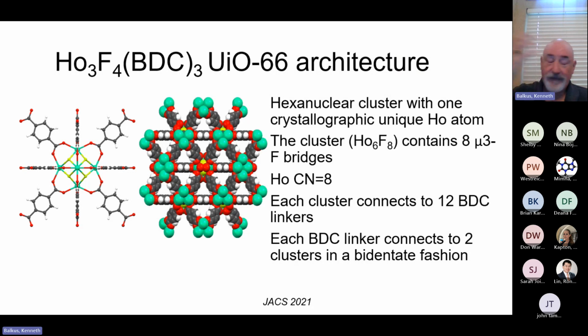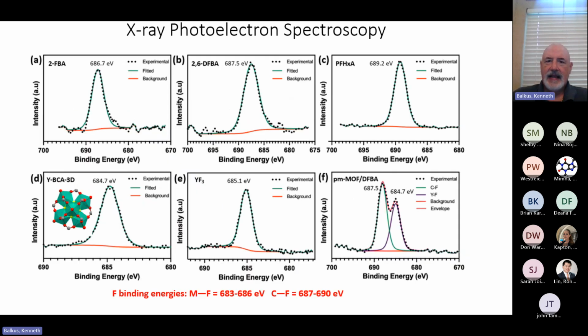And then the first question you ask is, is it really fluorine? Because if you think about where oxygen and fluorine are in the periodic table, in crystallography it's very difficult to prove that it's oxygen or fluorine. Fluorine fits better in terms of refining the structure, but it's not really proof. So we needed some other evidence that we were making fluoro bridge clusters. And for us, the best technique that we found was X-ray photoelectron spectroscopy.